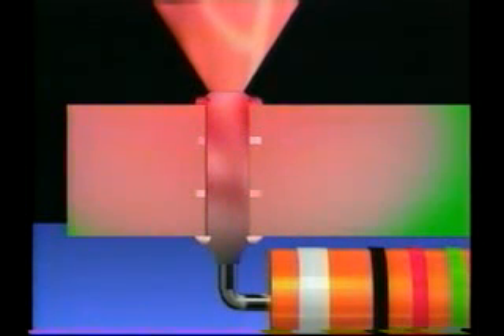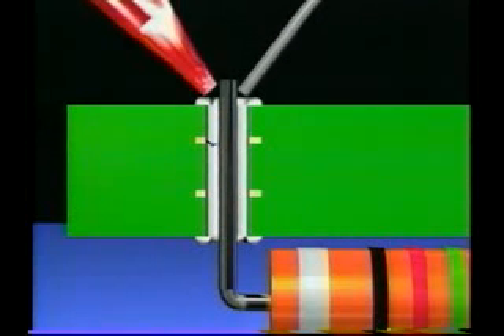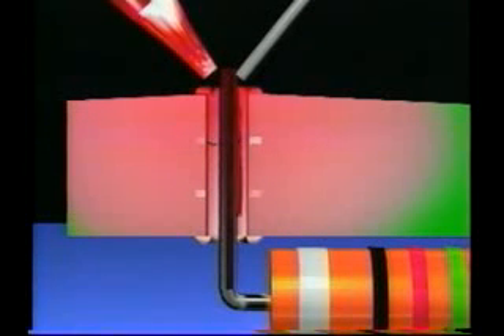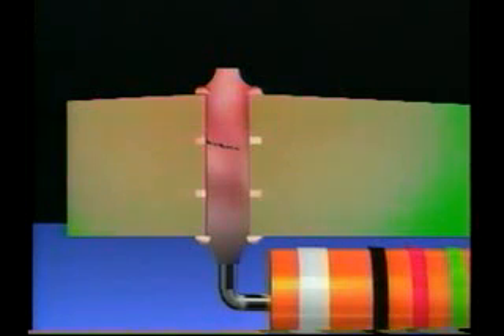What this means is that epoxy laminate will expand much faster than the copper during solder rework. When the laminate grows, the copper can actually crack if it's not soft or ductile enough to absorb the expansion. And most rework operations will require two heating cycles, one to remove and another to replace the solder. That's two extra chances to create internal cracks in the plated through holes. On multilayer boards that have internal connections to the interlayer circuitry, even a small crack can cause an electrical open or intermittent failure. This type of internal damage will not even be visible to the rework technician.